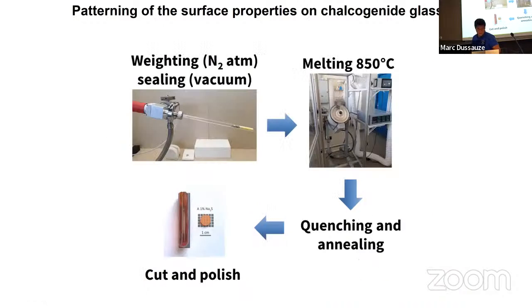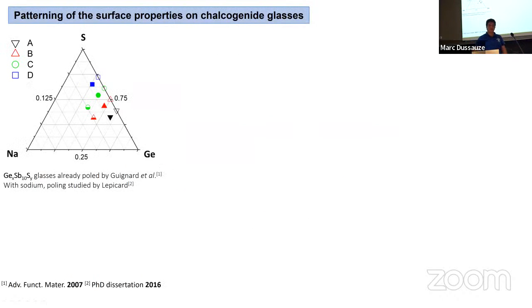To prepare this kind of glass, of course, if you don't want oxygen, you don't want water, you don't want anything, you need to prepare everything under controlled atmosphere. So everything is prepared in a glove box, then it is sealed inside silica tubes and then melted to get the glass, as you can see here. Okay, so we take this kind of glass and we have studied this ternary diagram where you have germanium, sulfur, and sodium. So we play with different compositions, changing either the sulfur content or the sodium content.